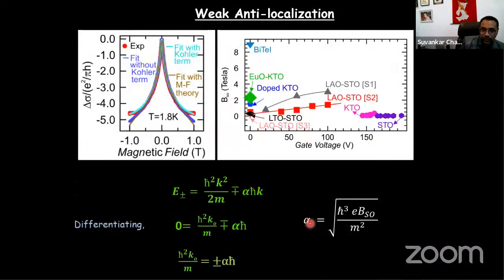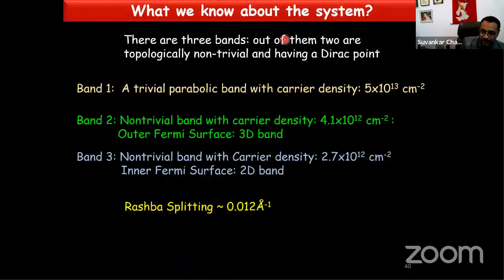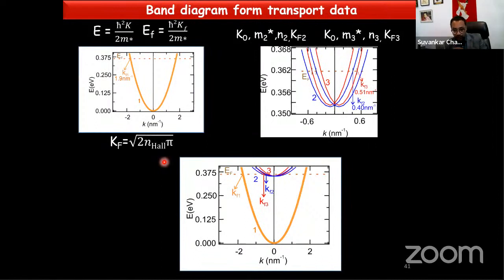And also we could see the strong appearance of weak antilocalization and strong spin orbit coupling as well. So this gives us the idea that we have 3 bands in the system: one trivial type parabolic band, one non-trivial band with Berry phase, which has a 3D type nature, and another 2D type band which is also non-trivial in nature. Then by using complete transport properties, we could figure out the possible band structure of the system.